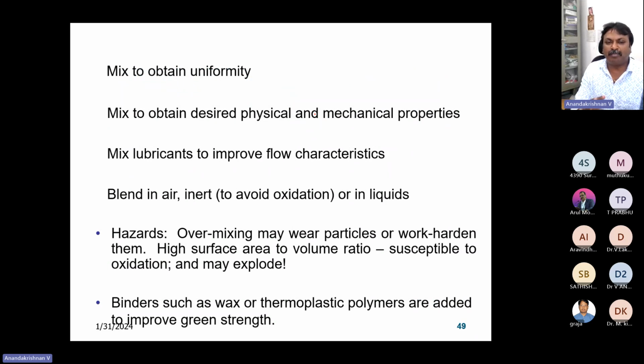So you have to mix it uniformly. A lot of physical and mechanical properties depend upon the mix. Now in 3D printers, when you are using powders, we have to wear masks. These masks should protect you from the powder particles. If the powder particles are less than a few microns, 40 microns, they can easily float in the air. Usually nano powders can float in air. If you inhale it, it can soak into your alveoli sacs, leading to a lot of respiratory disorders. People may even die. So you need to have a hazardous environment setup. You have to be very careful about that.